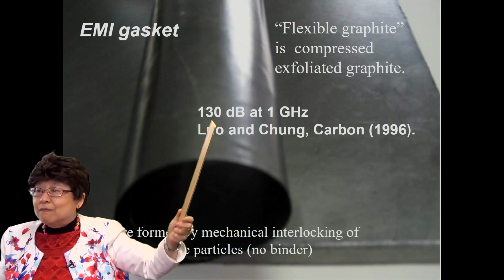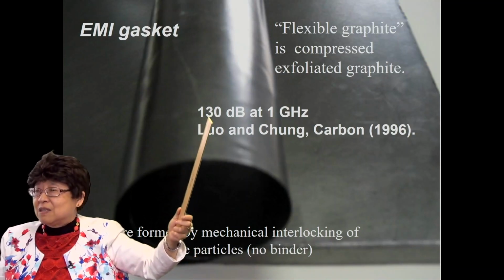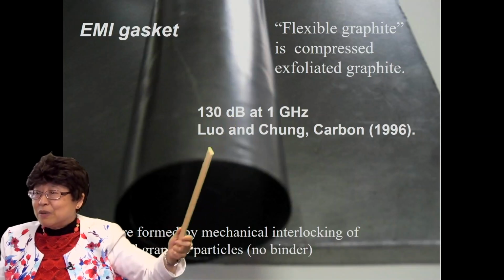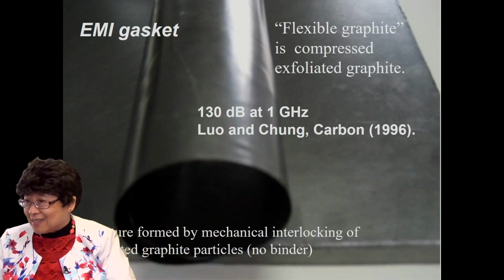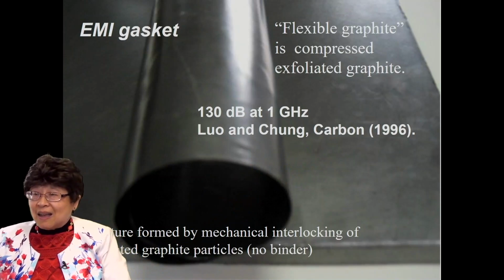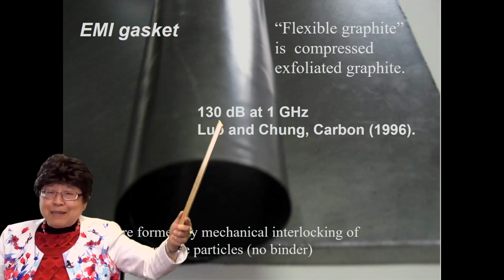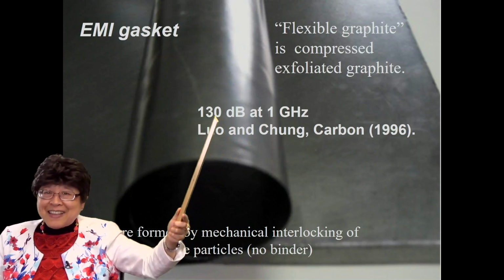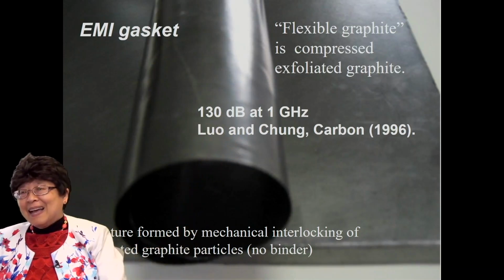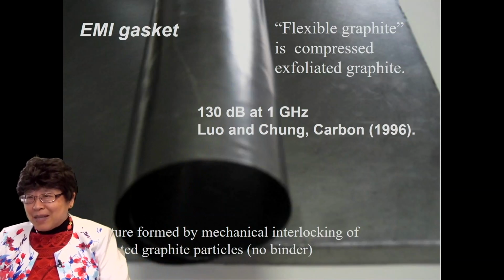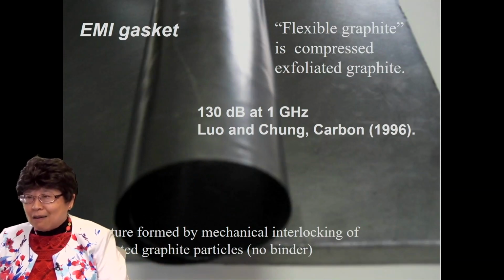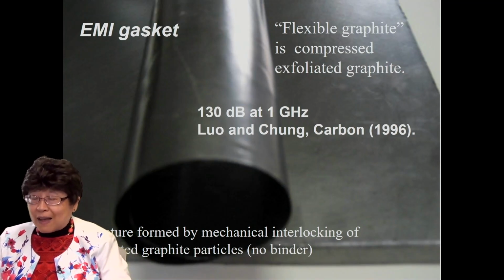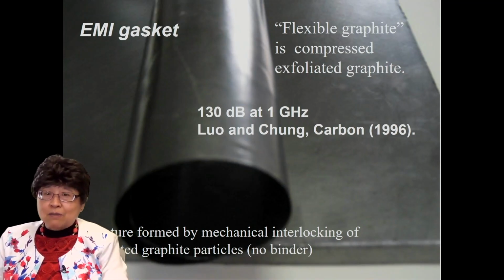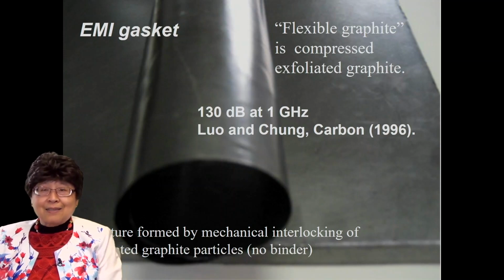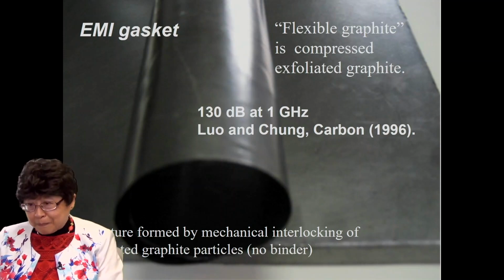And this material turns out to have very, very good shielding effectiveness: 130 dB. We reported that back in 1996, and it's still the record. In fact, this is the limit of feasible measurement. You can't measure it if it's beyond this. And the reason why it's so good is that not only is the graphite conductive, the flexible graphite, because it comes from exfoliated graphite, has substantial surface area per unit volume.